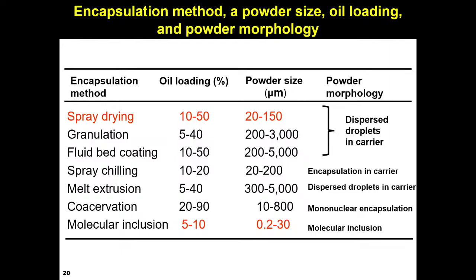With spray drying, oil loading is from 10 to 50%. But recently, for MCT oil powder, the content is 70%, 80% using modified starch. Powder size is 20 to 150, but usually around 100 micrometers, near 200 micrometers. Sometimes we can see small powder, but usually spray dried powder is above 100 micrometers. And you can see another type of powder, but mainly food powder is produced by spray drying.